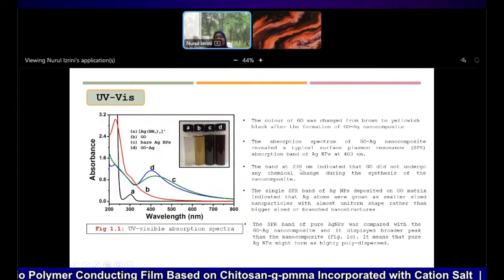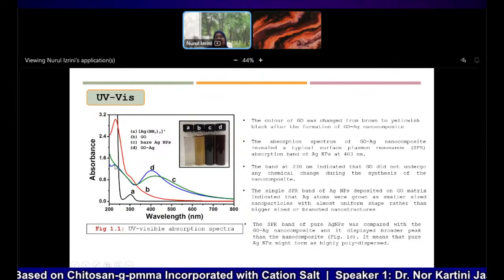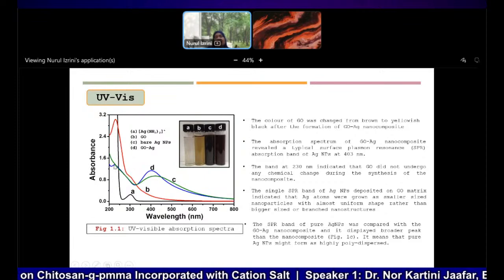However, the band at 230 nanometers indicates that GO did not undergo any chemical change. We can see this peak at 230 nanometers, which shows us that the GO is still maintained after 15 minutes of reaction. That's why we can say this forms the GO-Ag nanocomposite.